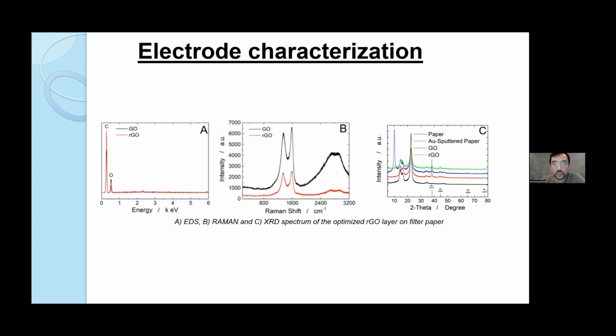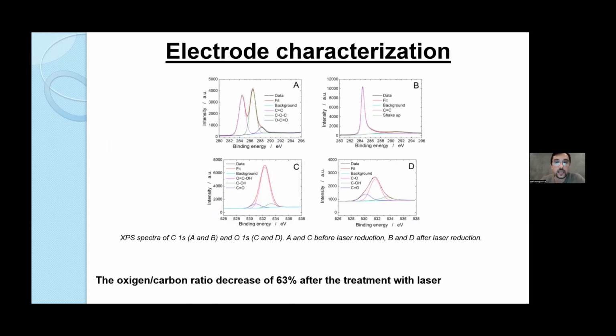So in order to find out this degree, we have carried out XPS analysis before and after reduction. And as it's possible to see, for example for the C1s spectrum, before and after reduction, there is a total disappearance of the carbon and oxygen bonds, such as C-O-C or O-C=O. So demonstrating that the electrode has been fully reduced, and using even the oxygen peak, we have found that after the reduction, the oxygen over carbon ratio decreases by 63%. So we have obtained a reduced graphene oxide electrode with a degree of reduction of about 60%. This is a very high result using a very cheap and easy protocol.